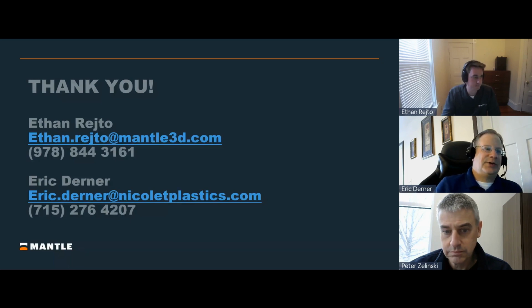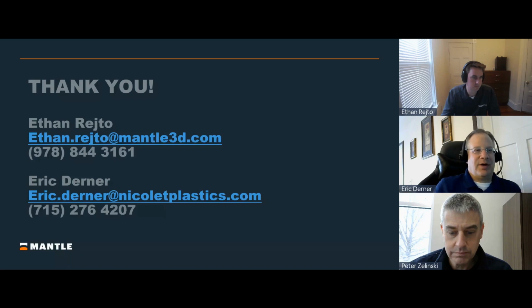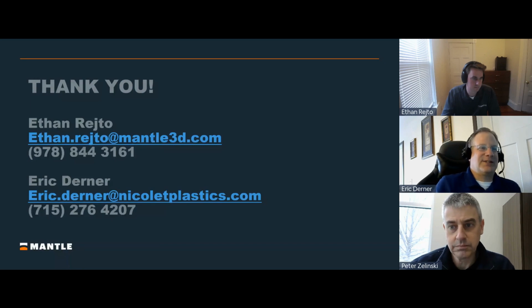This is what really intrigued Nicolet Plastics: the ability to print this without having a lot of induced stresses involved. You think about it from a thermal stress relieving standpoint. You get stresses added into the block even when you're machining normal tool steel, but here you're done with all those stresses after it comes out of the oven. So it's a really unique process. We found the blocks to be really, really stable.